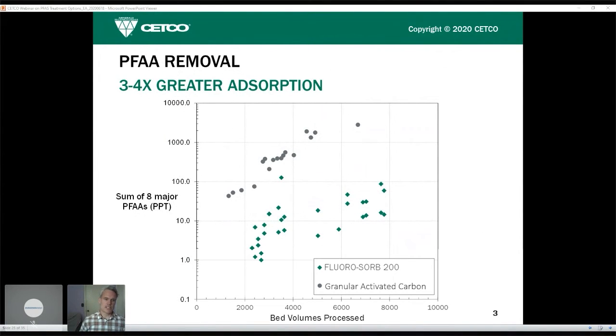So I'm not going to get into too much of the details of this experiment, but to show more of a summary slide. What we have here on the y-axis is a sum of 8 major perfluoroalkyl acids, and this is in the effluent of the column system. And then on the x-axis, we have bed volumes processed. So GAC system was run at an empty bed contact time of about 10 minutes. And then for the FLUORO-SORB, we were focusing on a 5-minute empty bed contact time. And I'll talk a little bit more about empty bed contact time in these adsorption systems. What we found was that it took a long time to get breakthrough for the FLUORO-SORB material, specifically relative to GAC. I think there's animation on this slide if you hit.